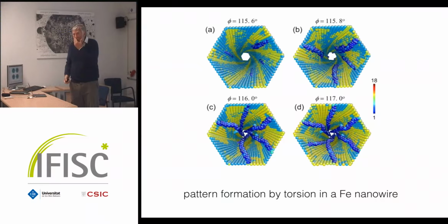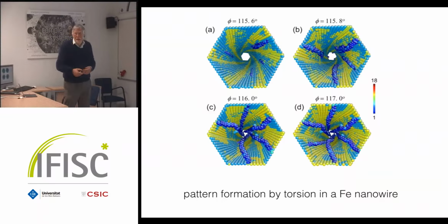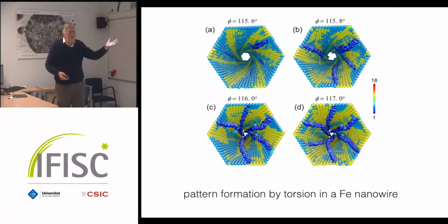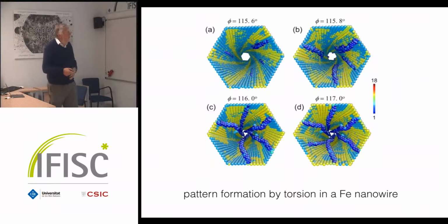You have to. Is this a hollow nanowire? Yeah, it's a hollow nanowire. And when you twist it, then you get these dislocation stuff in here. But the blue stuff here, which comes after some while, if you have twisted enough, are twin boundaries. Right? It's just the atomic configuration of what you create by twisting is again the twin boundary. And now, of course, here we can't have polarity because of the metal or whatever. But if there is polarity, then it will be in the blue areas here. So that's one part of research which is particularly done nowadays in China, where they take nanowires of all sorts, twist them, create these functional elements in there, and then test whether these functional elements can do something for you.